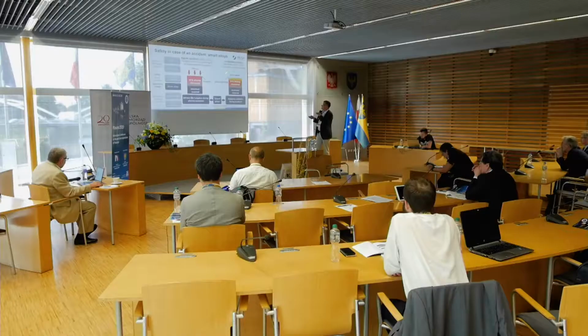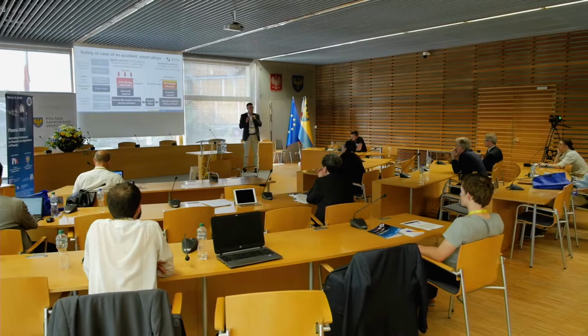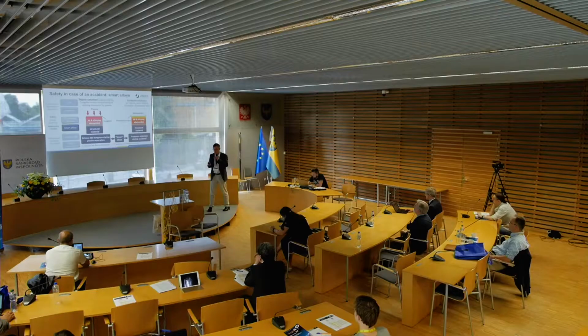However, in case of an accident, if we go to high temperature, we will lose this couple of nanometers. This is a very thin layer of depleted tungsten, so we cannot do much about this. But we will lose these layers, but we still have the alloying elements, which are chromium and yttrium, inside. These elements have a higher affinity to oxygen. They will create their own oxides much faster, and they will actually cover the tungsten, preventing oxidation and then subsequent sublimation. So this is the idea of the passive components for the power plant.